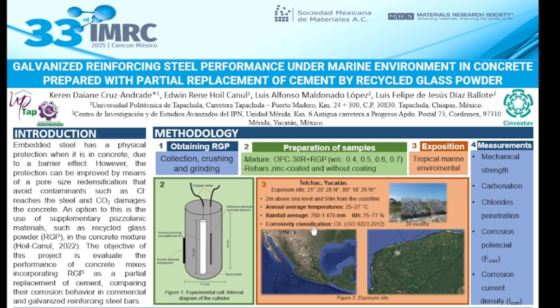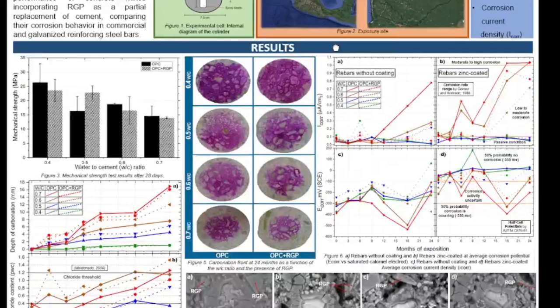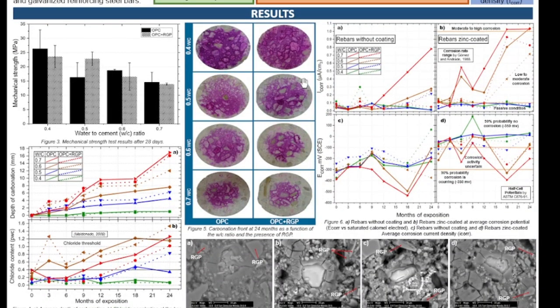this place is a highly corrosive marine environment identified by ISO 9223 in 2012 as classification CX in this case. And for the fourth step, measurements, the following tests were carried out: mechanical strength, depth of carbonation, chloride penetration, corrosion potential, and corrosion current intensity. For the results obtained, we begin with mechanical strength.